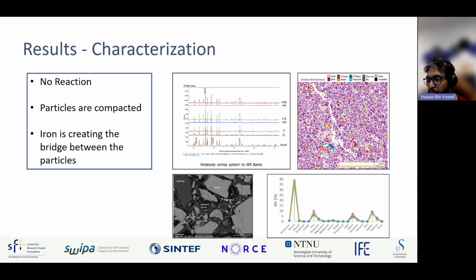And there is a lot of research where we found that in the downhole, due to friction, due to running pipes, a lot of iron came from the walls of our casings and the pipes. We believe that this iron goes in, mixes with the drilling fluid, and destabilizes it, and it settles down. Then the compaction, temperature, pressure, and all the other downhole conditions make this drilling fluid settle down, solidify, and create the sag barite.